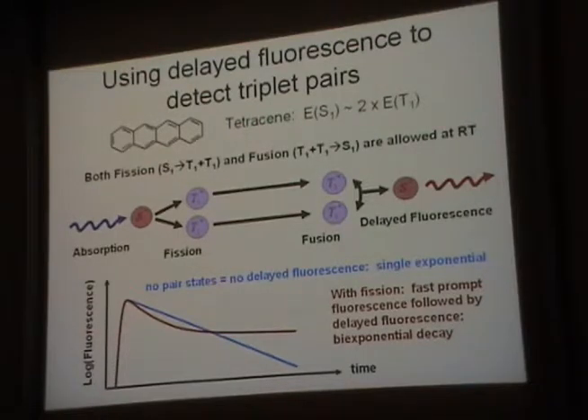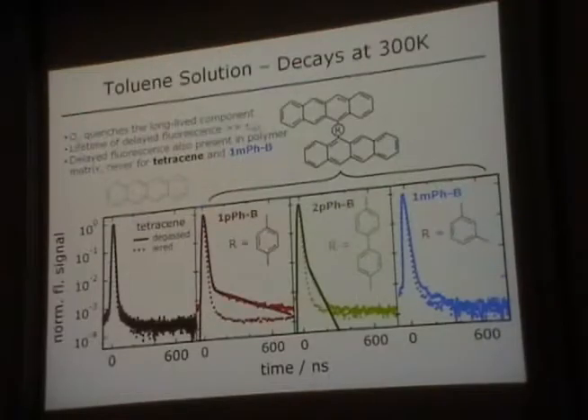So instead of seeing a nice straight line exponential decay, you see a decay, and then you see a second component that can last for quite a while. That quite a while is the triplet lifetime, the triplet pair lifetime in your molecule. And this is the only mechanism you can get to get this delayed fluorescence phenomenon in these types of molecules or in the solid. So this is a nice sensitive way to detect exciton fission, to detect the presence of triplet pairs. You just have to detect the singlet fluorescence, right? So you can look at very low yields, which is what we needed in this experiment.